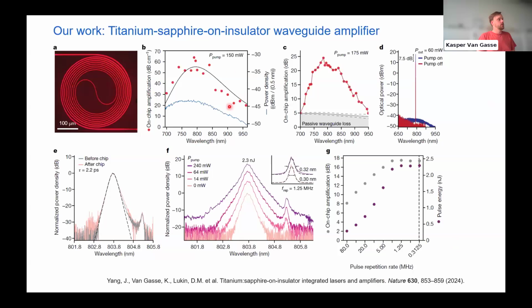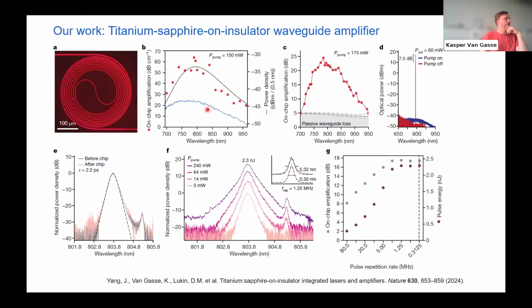And so here you see a small overview, and especially this picture is quite interesting. So this is a microscope image of the 8 millimeter long titanium sapphire spiral waveguide, of which the cross-section looks like this. It's pumped with green light and then long pass filtered to make the microscope image. And here we see it just lighting up in a very nice way.